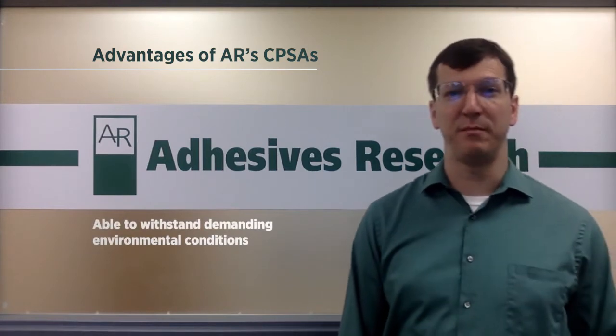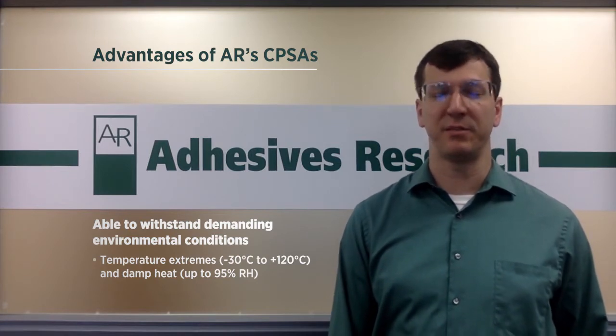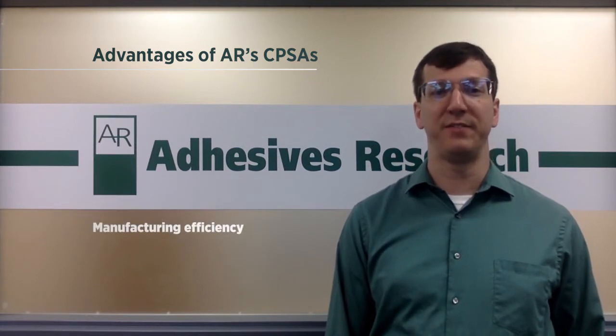We're able to withstand demanding environmental conditions with our PSAs. They can withstand temperature extremes from negative 30 degrees Celsius all the way up to 120 Celsius, and even damp heat with high humidities up to 95% RH. They're natively UV and chemical resistant to provide long service lives. And they can be designed with silicone, acrylic, or rubber adhesives to match the conditions and the performance requirements for each application.